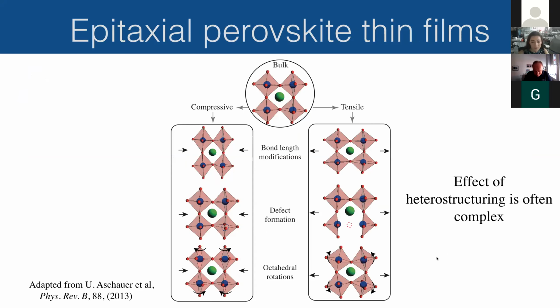What I want to mention now is specifically heteroepitaxial growth of perovskites. Because the perovskite structure, as I showed before, is very flexible and can take on different types of distortion, what actually happens when you grow this as a thin film is not always super clear. The naive picture would be that the octahedra just stretch or compress depending on the strain that you apply. But what can also happen is that you induce defects. If the strain is too much, this is very likely to happen actually, and this can be defects in the cations or in the oxygens. And finally, something I will come back to a little further on, is that you can have octahedral rotations. So instead of the octahedron stretching and compressing to accommodate the strain, it will just turn rigidly.